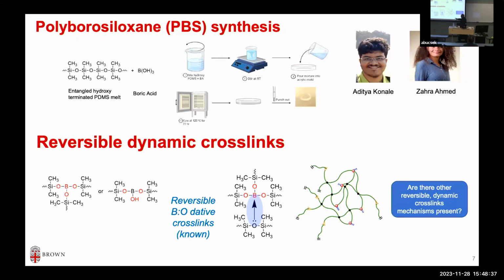if you look at this, polyborosiloxane is PDMS chains crosslinked by boric acid, and boric acid we used to play like a powder for the carom, I guess, when we were in India. So that chemistry allows these crosslinks formed between boron and oxygen. One electron pair is basically shared between boron and oxygen, and that gives us this crosslink that is time dependent. It's breaking and forming, breaking and forming. These crosslinks give the dynamic nature.